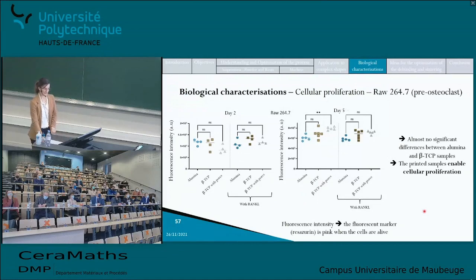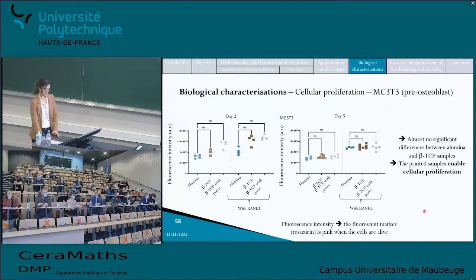The same results were obtained with the MC3T3 cells, because the first ones were done with the pre-osteoclasts. And here there was, again, no difference between the alumina samples and the β-TCP samples with and without pores. So again, these cells could proliferate on the printed samples with the optimum composition.